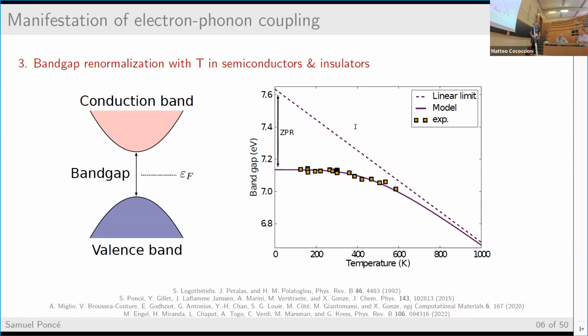This is the case of diamond. In diamond, this is very strong. You have something like maybe 0.5 eV renormalization. So if you neglect electron-phonon coupling, you are overestimating your band gap quite significantly. Then as you increase temperature, you excite more phonons and so on, and the band gap decreases even further. Again, it is possible using linear response theory to compute this effect, the band gap renormalization in semiconductors.